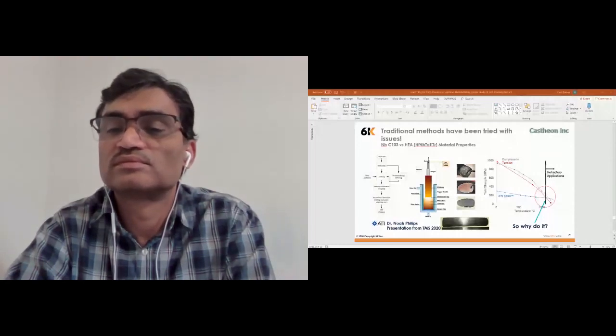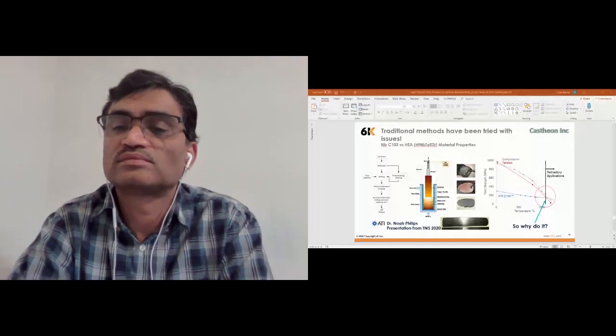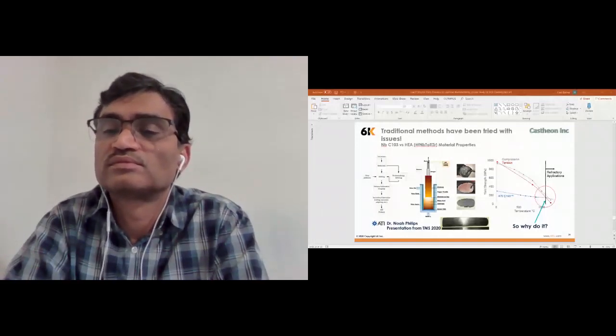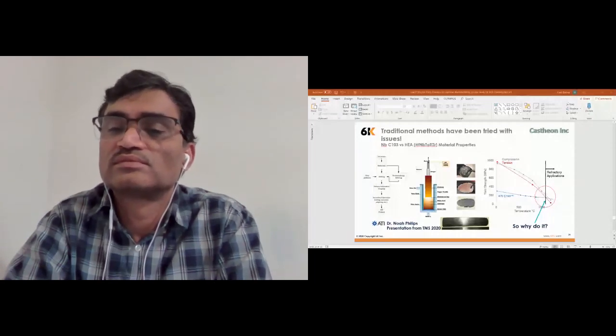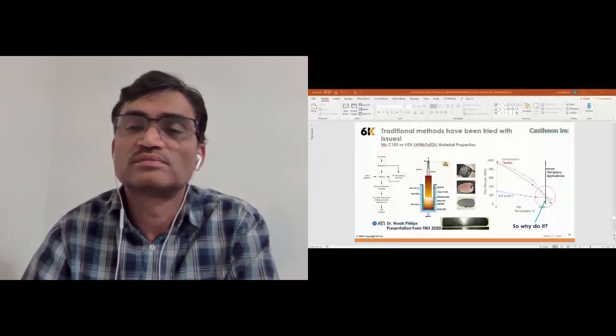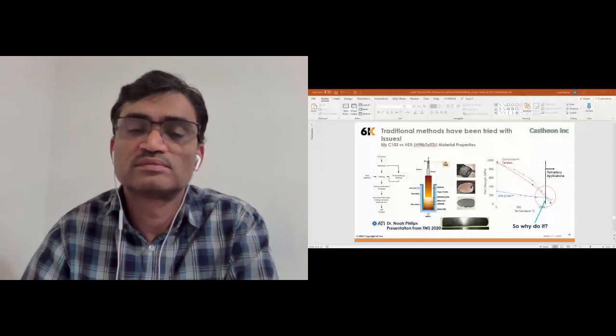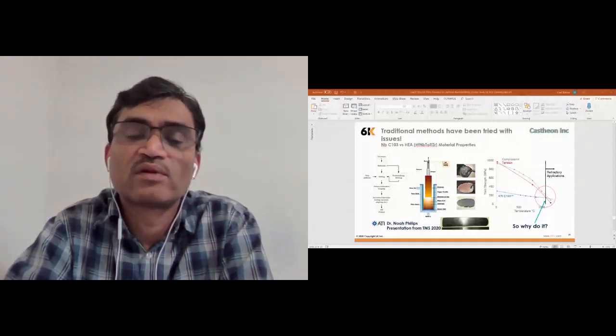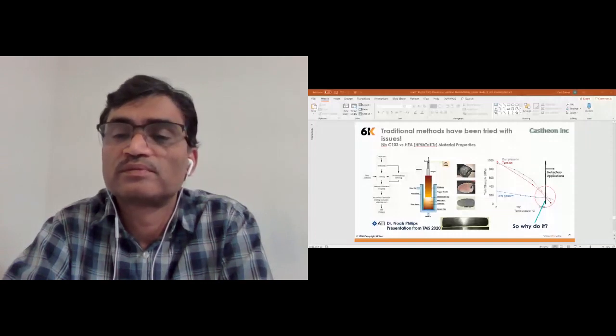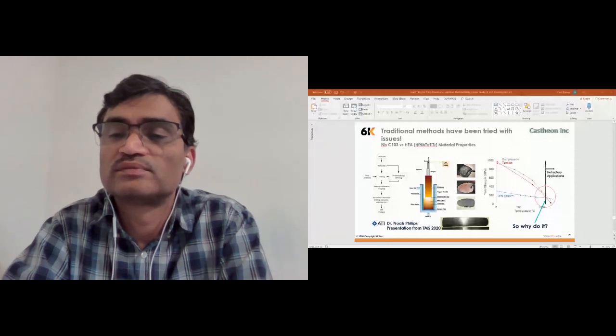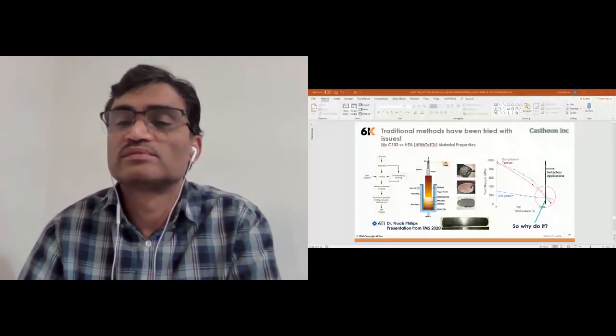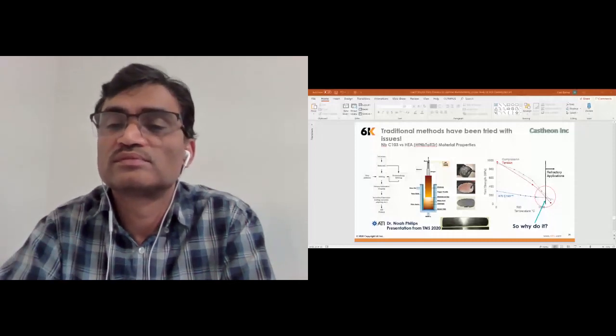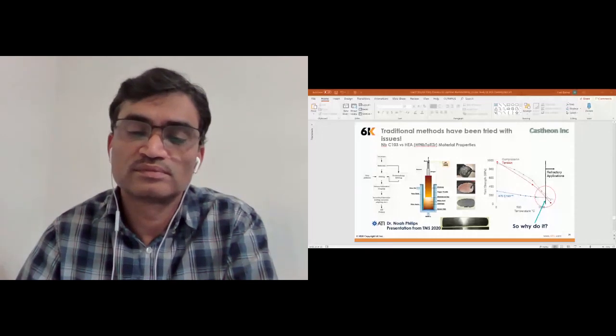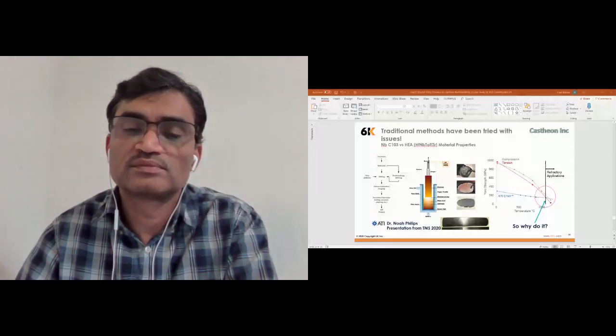After this alloy is made, you can see the performance in comparison to the traditional niobium C103. At a temperature where we need this high temperature performance, we found this high entropy alloy not performing well. So the optimization process requires a lot of alloy element adjustment. And this can only be possible with the digital alloy through the powder metallurgical process. Otherwise, if you want to go through the traditional alloy making process, it's so expensive, it's almost impossible.